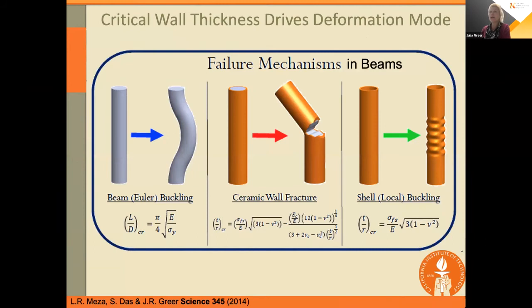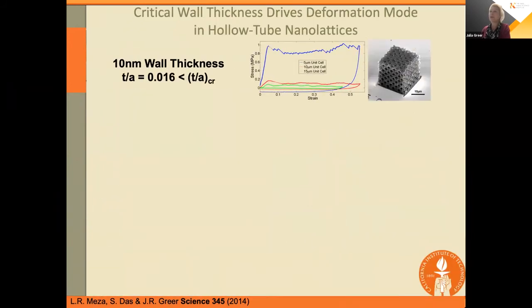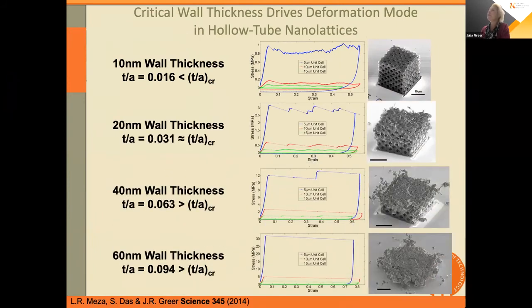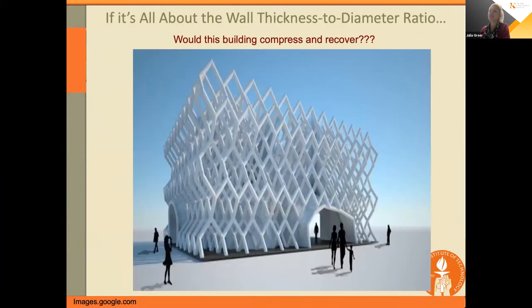So in the interest of time, I'm going to skip over some of the mechanics that I was going to show you, explaining how the size effect manifests itself in these architectures. And it has a lot to do with susceptibility to defects. For example, this recoverability is a phenomenon that would be present only in materials whose thickness is maybe 10 nanometers or so, wrapped around a very large architecture. In contrast to a giant building like this, which, and I'm sure there's a building like this in Singapore somewhere, if we were to preserve this self-similarity of the ratio of the wall thickness to the radius of the concrete pipes that comprise this building, and some giant were to come and step on this building, of course, it would never spring back like we're observing in our nanostructures.